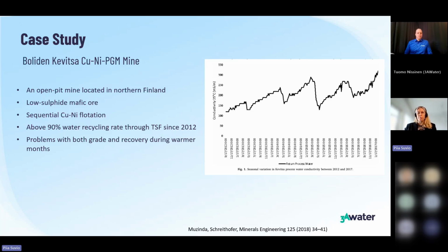And you can see here on the right what happened when they closed the loop, so to speak. The conductivity of water started to alter between different seasons. Going from the spring towards the warmer months, the conductivity is increasing and then it starts to decrease again, but with a delay going into the winter months. So here we can see that the impact of water quality carries over further from the period where it occurs. And what they discovered is that they had problems with both the grade and the recovery during these warmer months. The impact of the high conductivity that started to increase in the spring was really seen in the summertime even more.